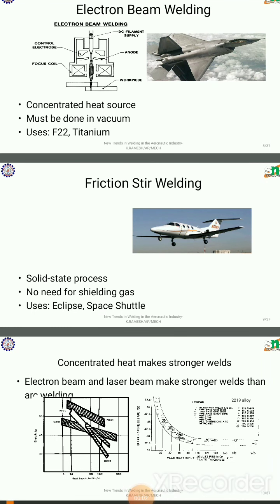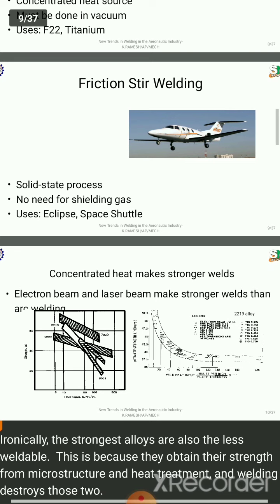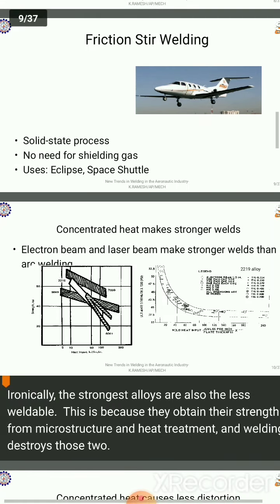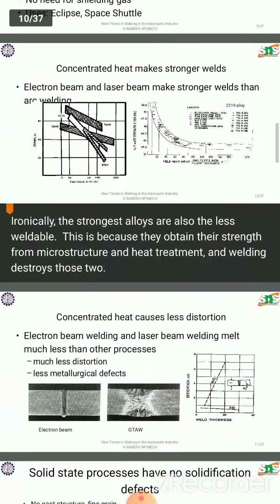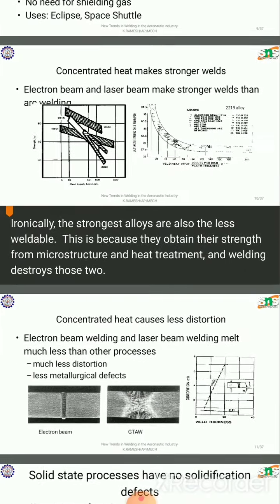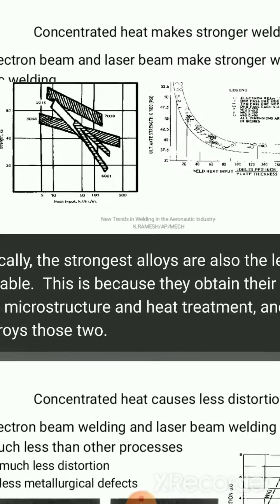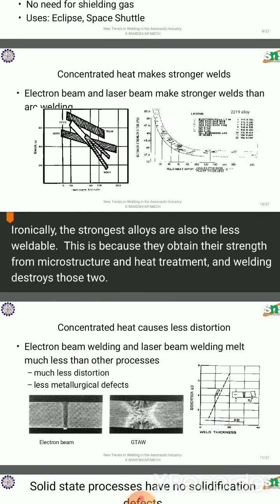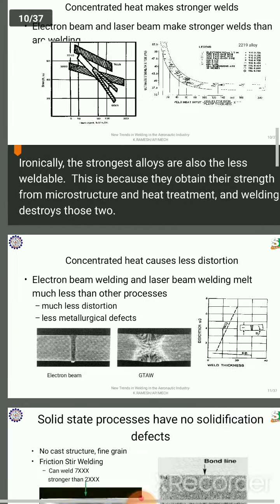Electron beam welding, friction stir welding. Friction stir welding is a solid state process, with no need for shielding gas. Used on the Eclipse and the space shuttle. The electron beam, the concentrated heat, makes a stronger weld. Electron beam and laser beam make stronger welds than arc welding. The strongest alloys are also the least weldable. This is because they obtain their strength from microstructure and heat treatment, and welding destroys those two.